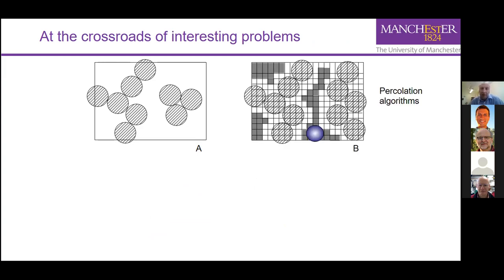The first problem is related to how this porosity is connected. For this, you can just divide the system into a set of cubelets and use percolation algorithms like Hoshen-Kopelman or some other algorithms to understand what portions of this structure are connected to each other with respect to a probe of a particular size. Voronoi and Delaunay tessellations have also been used for this type of problem. So there's a variety of mathematics and interesting problems that are associated with the topology of the porous space.